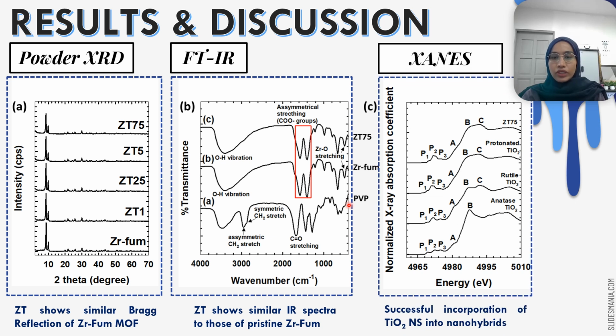And then, in order to prove the successful incorporation of TiO2 nanosheets in the nanohybrid, I characterized the sample with the same spectrum. So actually the TiO2 has a lot of phases such as anatase, rutile, and also protonated. Protonated TiO2 here belongs to the TiO2 nanosheets. And we can prove that the incorporation of the TiO2 is successfully done in this nanohybrid because we can see the ZT nanohybrid here shows similar spectra to that of the protonated TiO2.